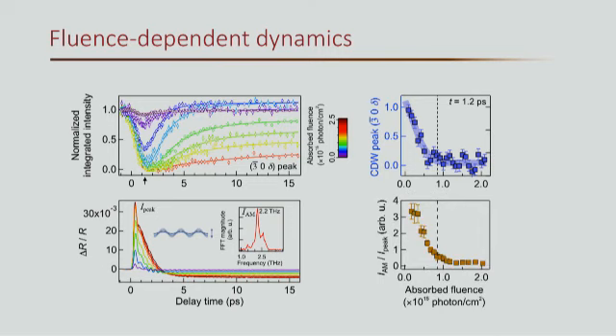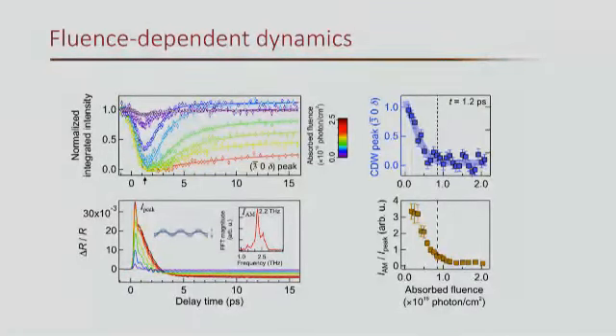And of course, we can also see how this oscillation evolves as a function of fluence. Do we still see this oscillation at very high fluence? So here we do the plot. We normalize the amplitude of this amplitude mode, I know it's awkward, amplitude of amplitude mode, by the peak intensity, where peak intensity represents how much pump power, how many quasi-particles we excite from the system. And again, we show a similar critical behavior: beyond a certain fluence, because of the loss of coherence, for example due to the suppression of the amplitude of the charge density wave as well as creation of many little phase incoherent domains, we no longer observe a very strong coherence peak from these modulations.